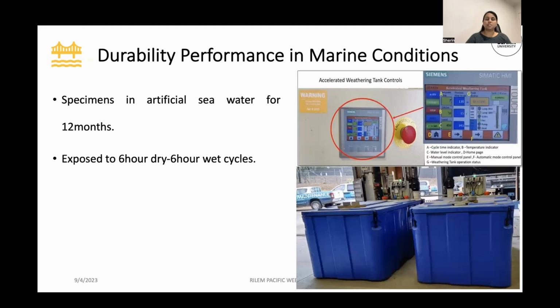We also expose this to 6-hour dry and 6-hour wet cycles. So what happens is in one of the tanks, the specimens will be in a fully immersed condition, while the other will be left for drying. And after 6 hours, this will alternate with each other. So at a time, Tank 1 will be immersed and the other one will be dry, and this will alternate every 6 hours to form the dry and wet cycles, which is simulating the tidal cycles. And to ensure proper drying, we have installed fan dryers, which are seen as the black blowers on top of the tanks.